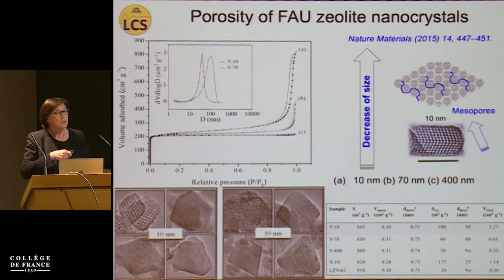This is the first example demonstrating that by decreasing the size of the crystals, we do not decrease the micropore volume if we ensure high crystallinity of the materials. The micropore volume of these ultra-small nanoparticles is 0.3 cubic centimeter per gram, which is comparable with the theoretically predicted value for faujasite zeolite. In addition, these nanoparticles, due to the close packing during drying, form the so-called textural mesoporosity, and the size of these pores is in the range of 10 to 50 nanometers.